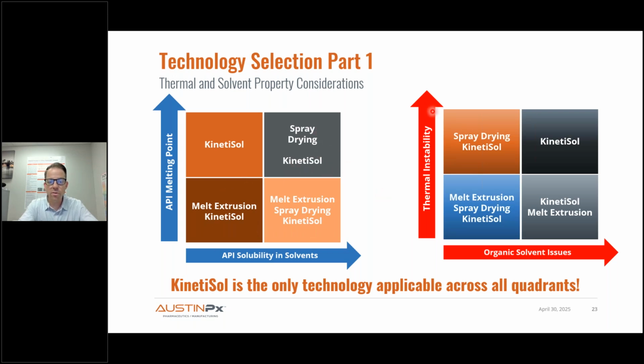applicable there. So now let's also look at it as thermal instability versus organic solvent issues. Now, I don't have the time to go into organic solvent issues, but any of you that have worked in spray drying know what I mean when it comes to organic solvent issues. So if you've got a molecule that's thermally unstable, and it's got a lot of issues, whether that be solids load or your organic solvent is chlorinated or it's THF or something nasty, you're sitting up here in a quadrant where KinetiSol is probably your only option. And then as you go around this grid, once again, you can apply spray drying and melt extrusion, but KinetiSol is also applicable. So the take-home message here is KinetiSol is the only technology that's applicable across all these quadrants.